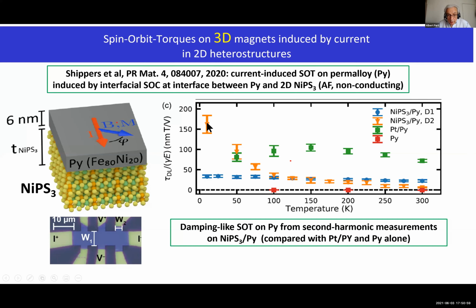Of course, as a function of temperature, this effect disappears rapidly because the ordering temperature of these 2D magnets is relatively small, and at room temperature, platinum is better, of course. So, finally, to summarize, we have seen that the spin orbit coupling, which is always large in these 2D magnets, can be exploited to obtain spin currents, to generate spin orbit torques, and for example, to be used in devices like SOT RAMs. Of course, the condition is to solve the bottleneck of the low temperature of these 2D magnets.